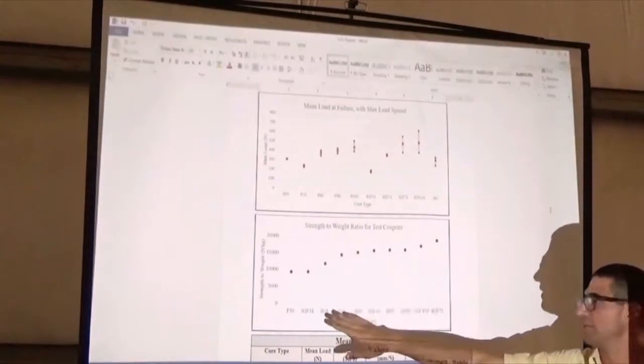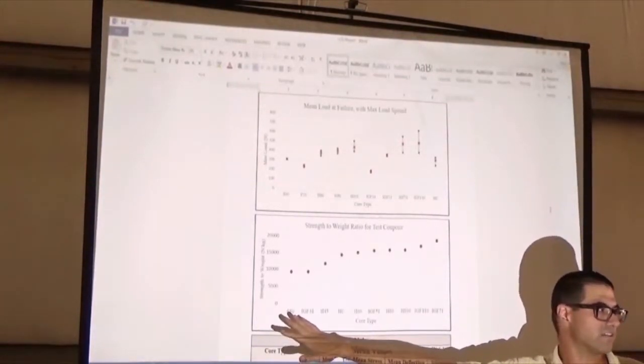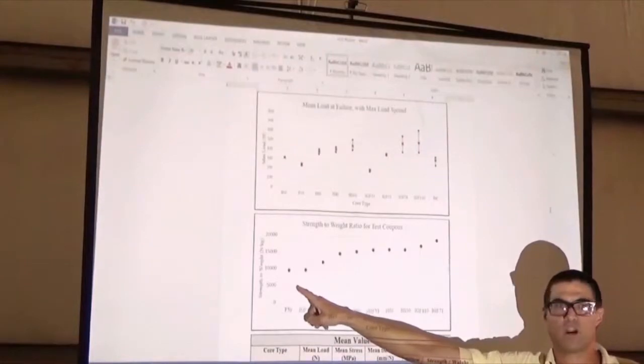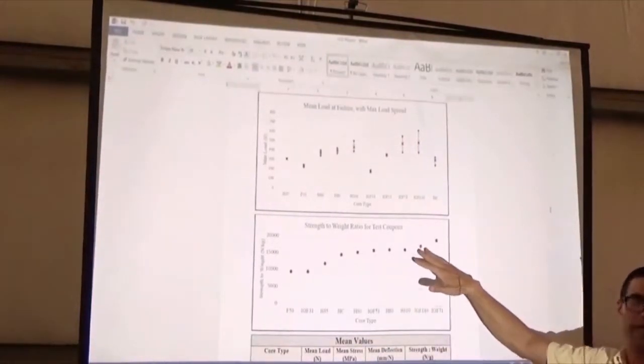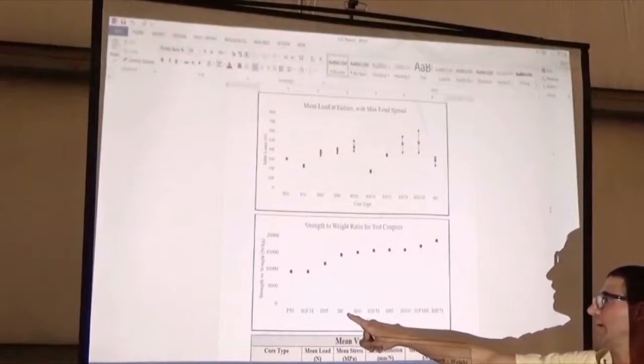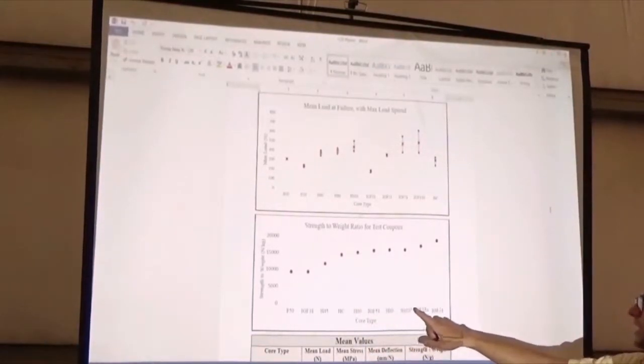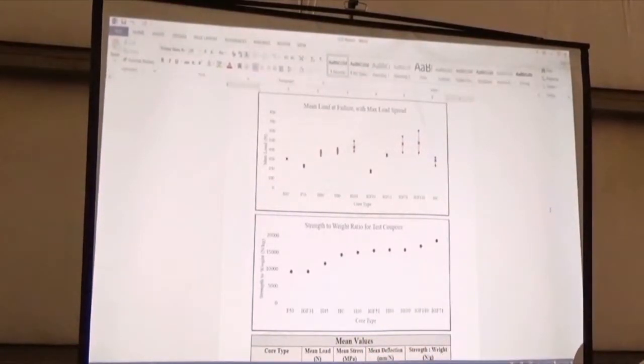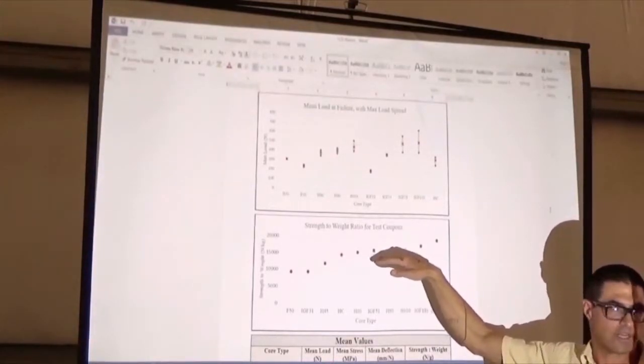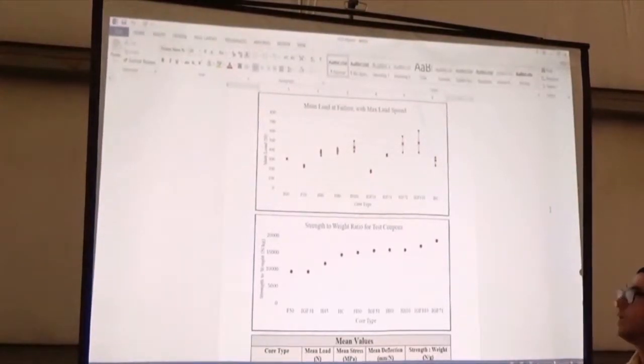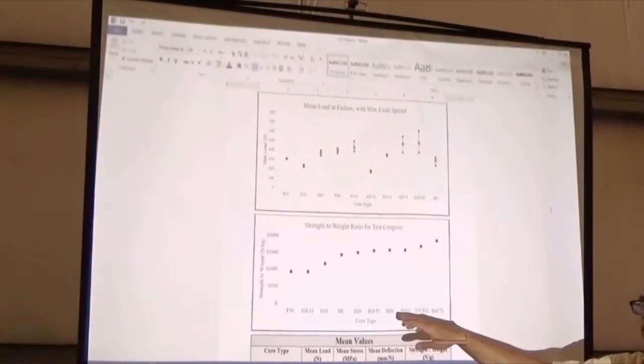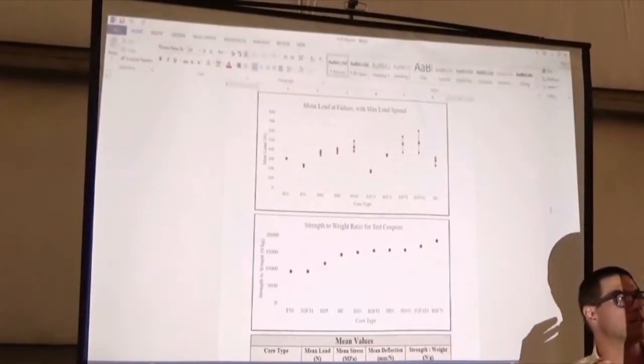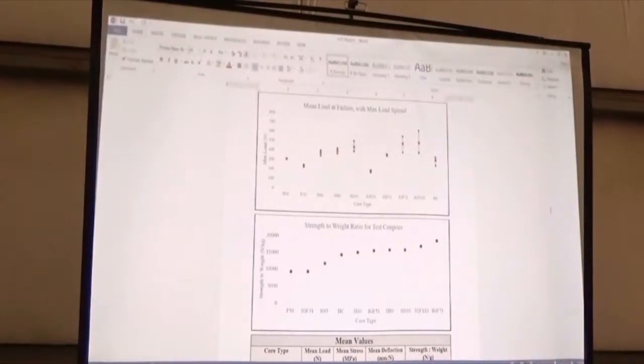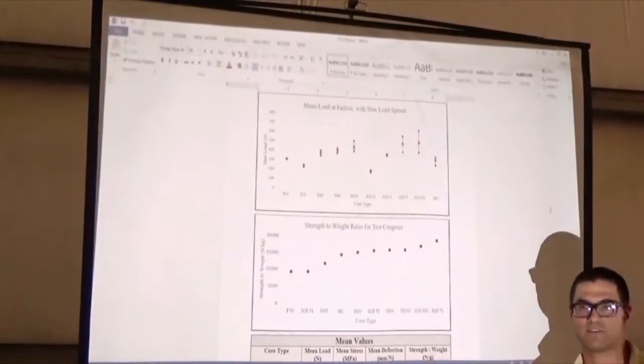Another interesting thing you can see is that when you get into the really lightweight grades of foam, you have a drop off in strength, and then it kind of plateaus. And so between like H60 and H100, you get pretty similar results. And this is strength to weight, so it's just kind of an arbitrary, non-dimensional measure of how strong these particular coupons were. But what it indicates is that you can kind of tailor the strength of your part by increasing the density of the foam, if that makes sense.